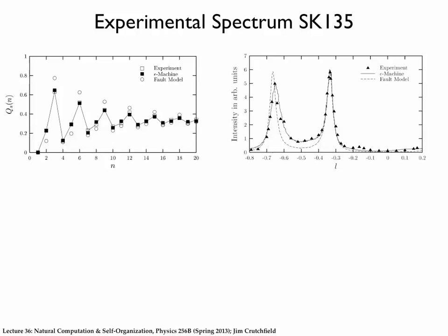When we look at the diffraction spectra, we find that the fault model really misses this peak a lot. I mean, it goes way up here when it doesn't do that. We do a bit better in getting this one. We also get this broadband diffuse scattering in between these two peaks, which the fault model really doesn't get so well.